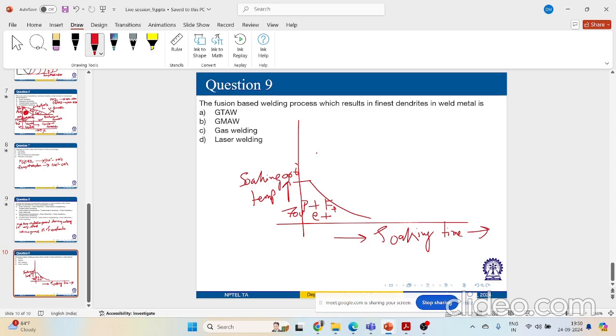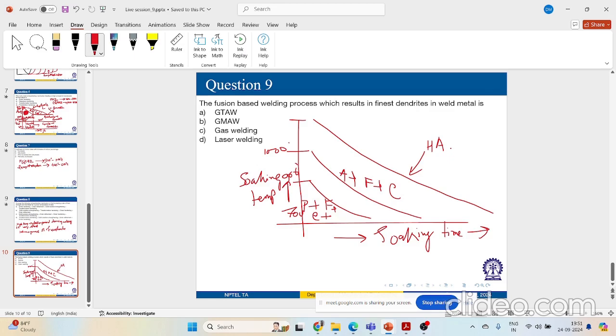Now, as you are increasing your soaking time, I will be forming more austenite, ferrite formation, cementite formation. This is somewhere in the range of 1000, let's say. Now, as you are going beyond 1000, let's say at a temperature of 1200, and you apply more time, I will be forming homogeneous austenite all over, right?